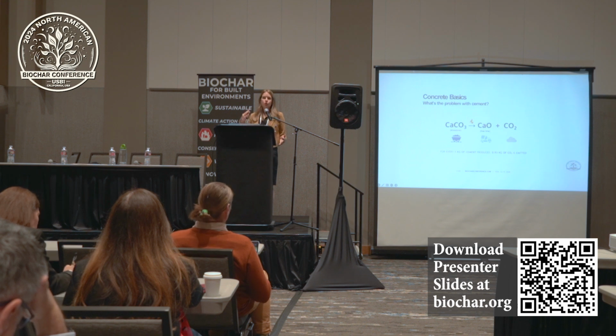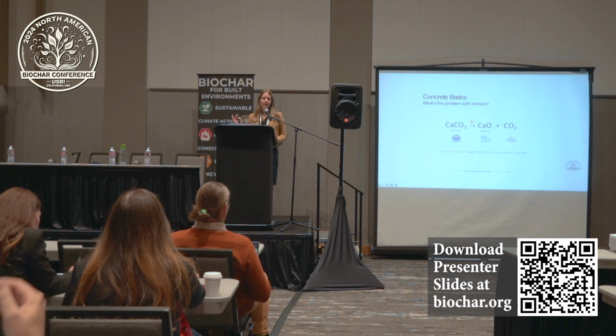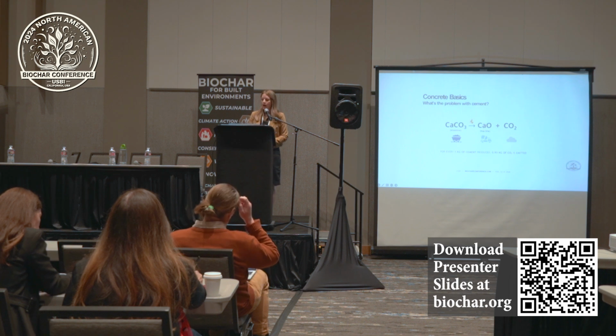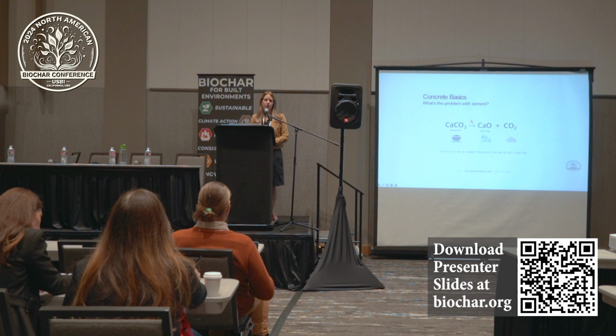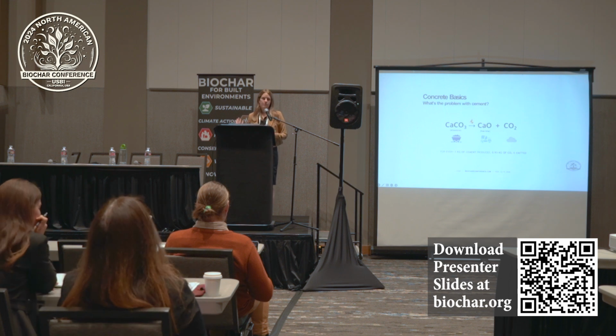So huge supply, and that's where we're getting that 8% number. And that's really tied up in the manufacturing of the cement powder itself. So when we manufacture cement, we mine limestone, we take it, heat it up to get free lime, and that's what we want in our cement powder.